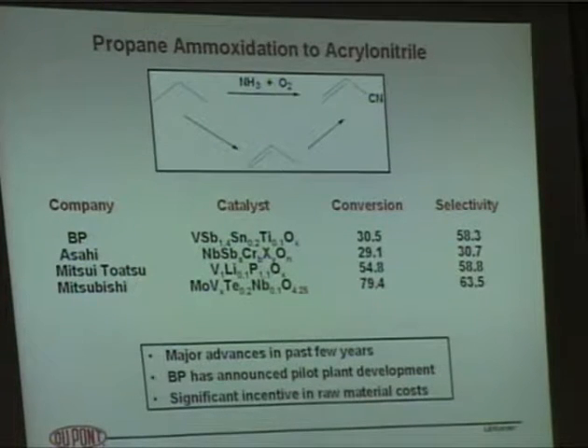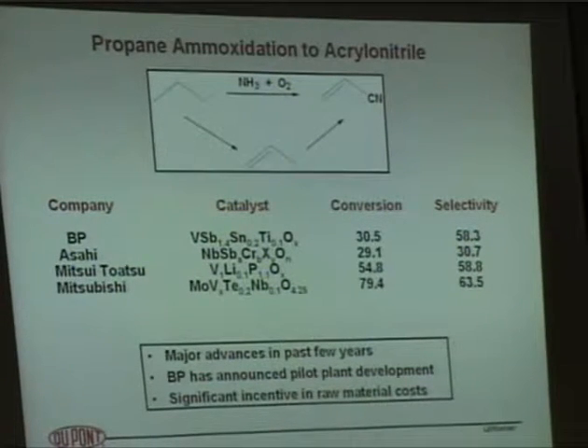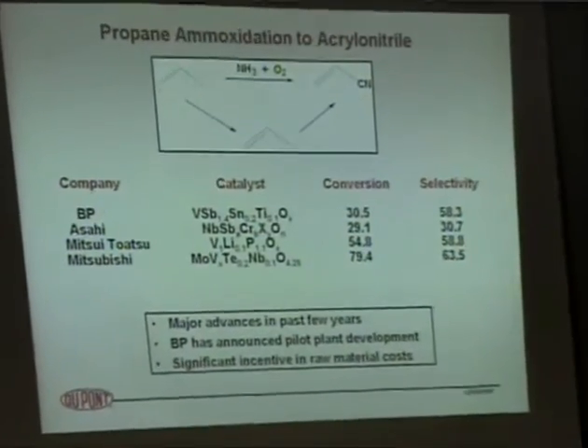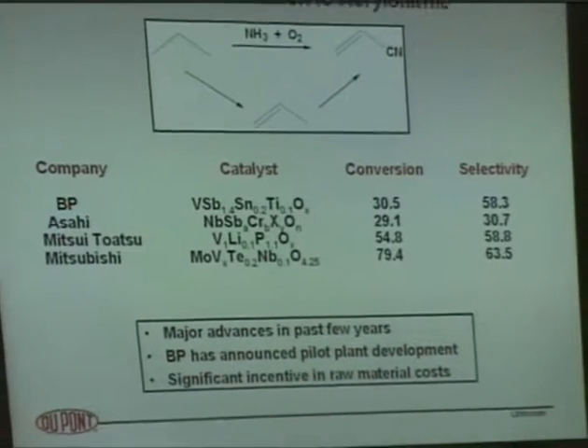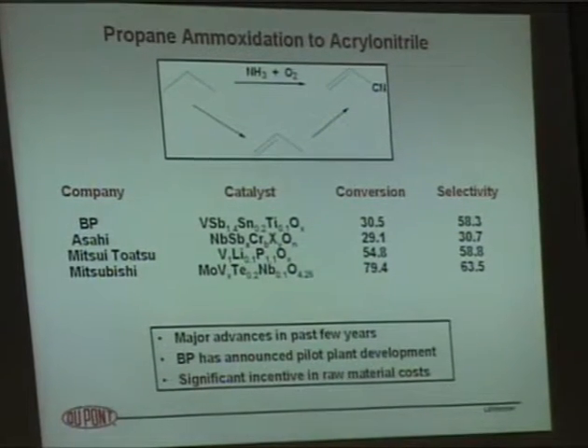Conversions are now up close to 80%, going directly from propane to acrylonitrile. Selectivity is still not where we'd like it to be, but in the mid-60s, which is pretty remarkable to go in one step from propane to acrylonitrile. So there have been some significant advances there. Propane is a lot cheaper than propylene. The economics look pretty good for this process. BP has announced that they are actually building or operating a pilot plant in this area, and the economics look attractive at specific locations in the world where propane is readily available.